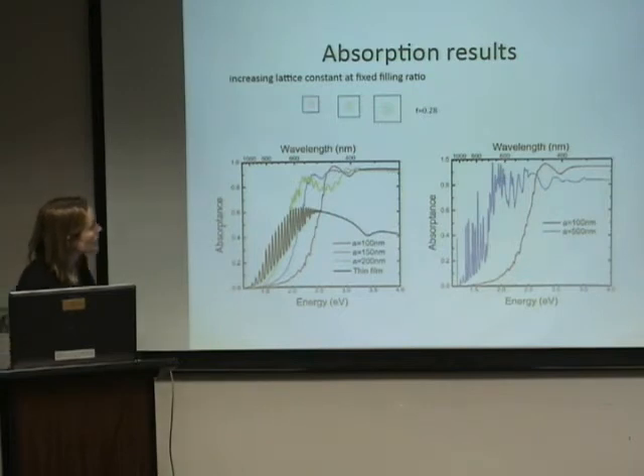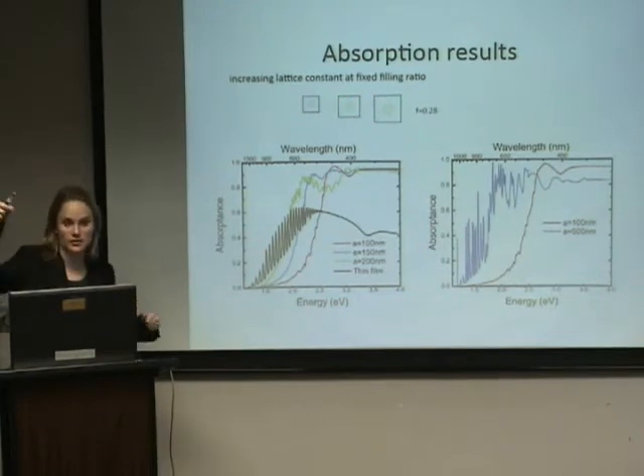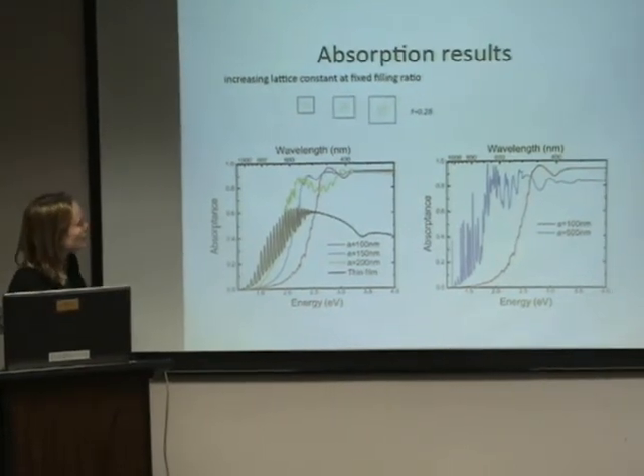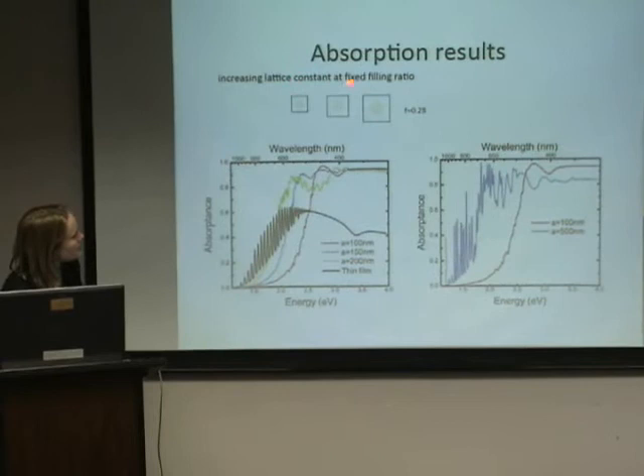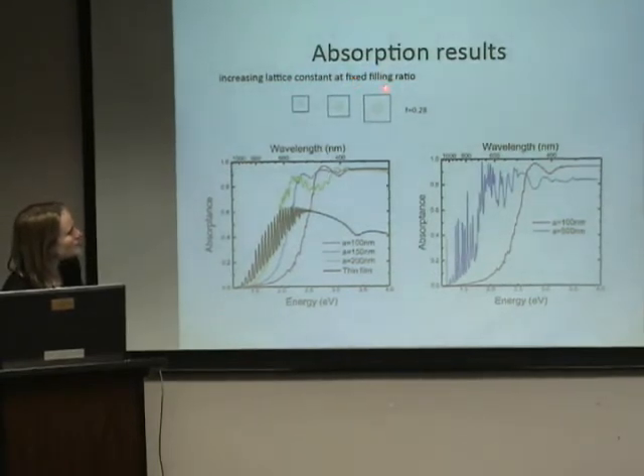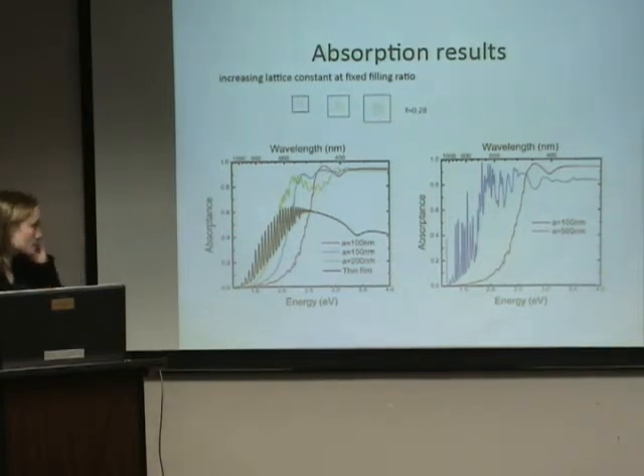What we did then was we calculated results as shown here. This is very light gray on this slide. This is a rod, and this is the unit cell. Here the rod gets bigger and the unit cell does as well, so we're scaling the whole thing up. So we increased the lattice constant while keeping the filling ratio constant. The filling ratio is the area of your rod over the area of your cell. And the results are shown down here.